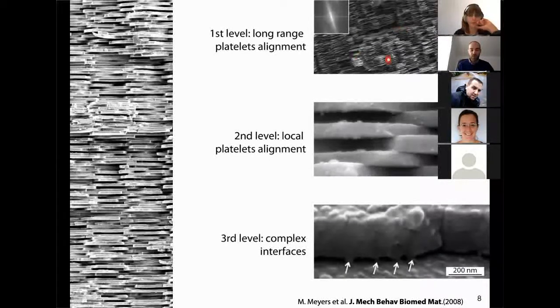The first thing we can look at is the long-range platelet alignment. Over very large sizes, all these tiny platelets are perfectly packed together and perfectly aligned. If you zoom in more, while the platelets are very fitted together, you can even see that some of them are interlocked with each other. Finally, if you look at the interface, there's a real challenge to image that correctly, but you can see that it's extremely complex because you have mineral bridges going on here, and you have the protein layer there. So you have a continuity in all the structure, a continuity of the mineral phase, even if you have some interface in between, some protein layer.